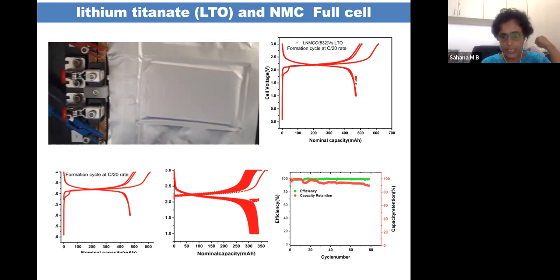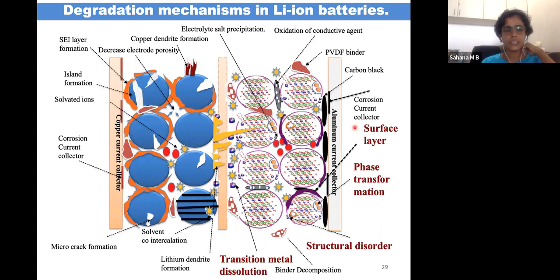Now, why does this loss happen? I'm showing one of the not so good cells. The loss in capacity can come from various reasons. Now, if you see, this is the degradation mechanism of a lithium ion cell. There are almost 20 to 30 parameters that can degrade the cell. I'll give a few examples here.